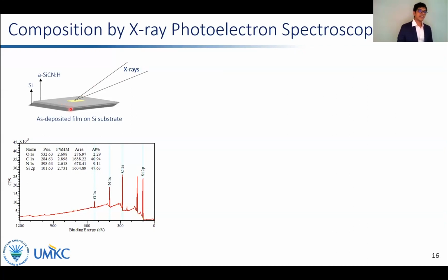XPS was acquired on as-deposited thin films after sputtering the surface with argon to remove adventitious carbon, so that we are probing the bulk of the thin film.